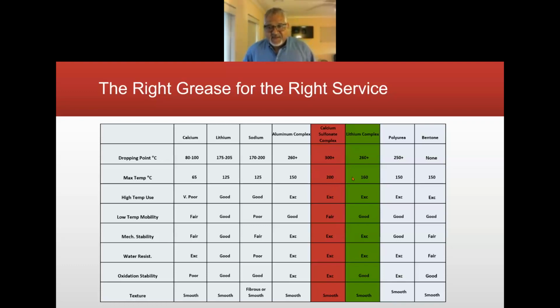Maximum operating temperatures are typically higher. These are synonymous in terms here. They're both good for, quote, high temperature use, but that's a discretionary term. What is high temperature? Because they'll both fail at extreme temperatures over 500 degrees Fahrenheit for sure, even 400 degrees Fahrenheit. Low temperature mobility, again, we talked about that a couple of times already. I just stay with the industry tagging of calcium sulfonate as fair for low temperature mobility, but you can definitely formulate calcium sulfonate grease for good low temperature mobility. Mechanical stability is definitely better for calcium sulfonate. It's still good for lithium complex. So the industry calls them both excellent.